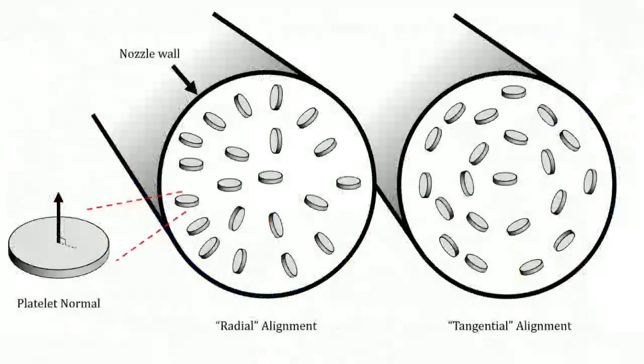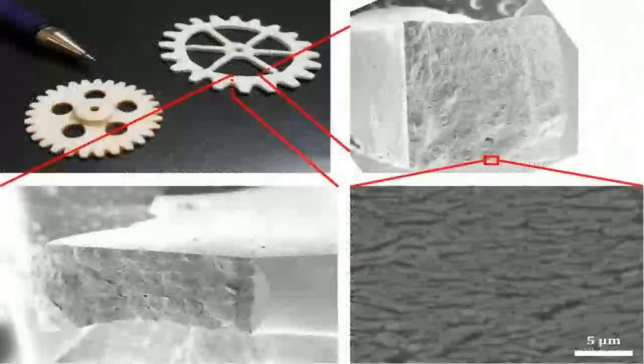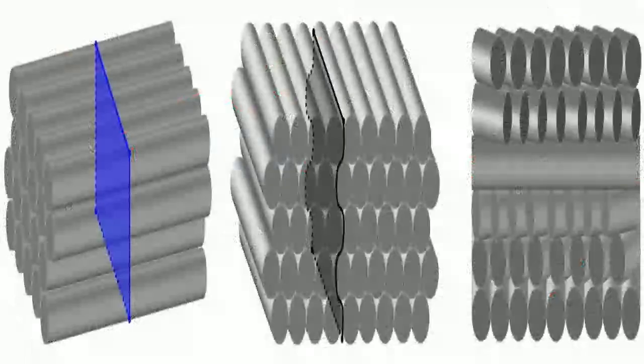They tried the more direct approach here, mixing the short carbon fibers directly into ceramic matrix paste like alumina or silicon carbide, then trying to sinter these parts at high temperatures to densify the ceramic matrix around the fibers. And the main problem was? That's difficult, fiber degradation. Big time, during the high-temperature sintering process, which is necessary to make the ceramic matrix dense and strong.